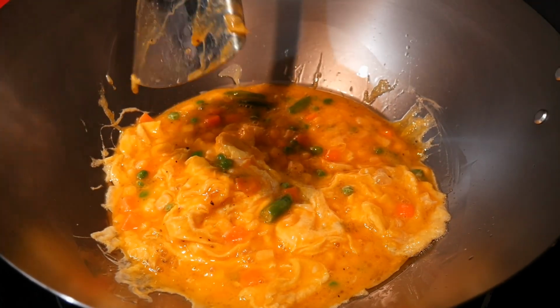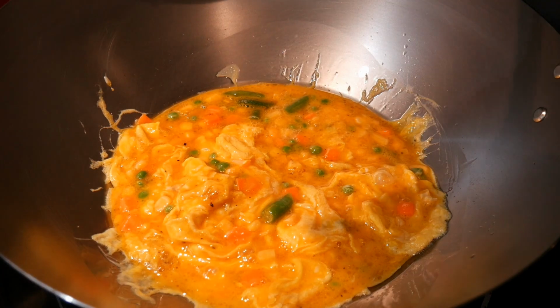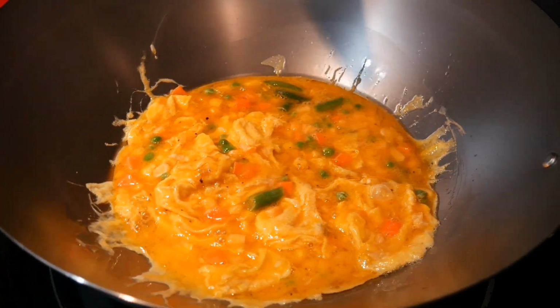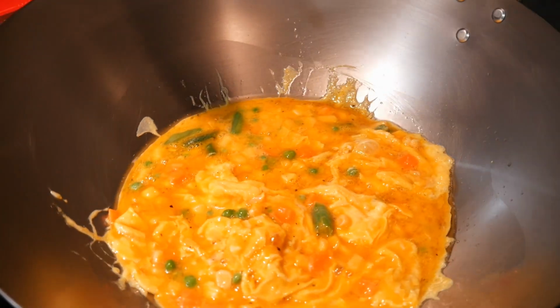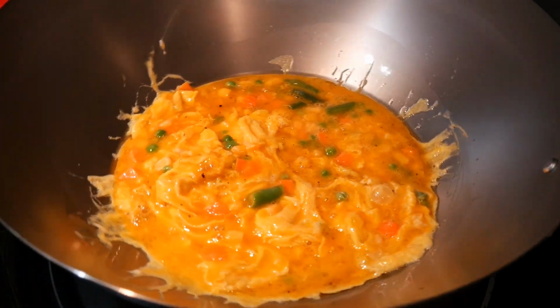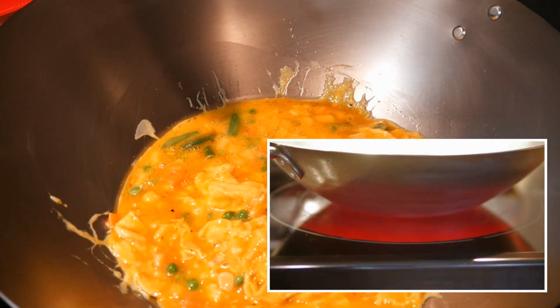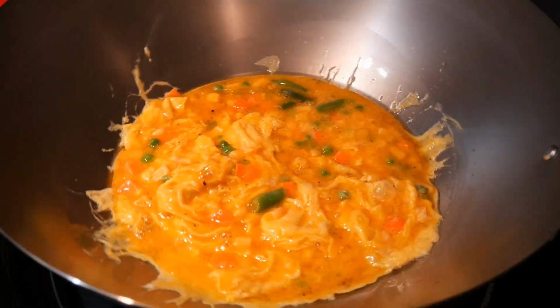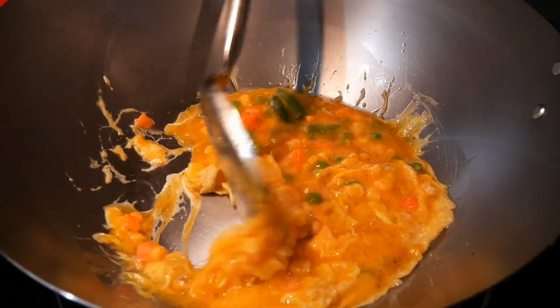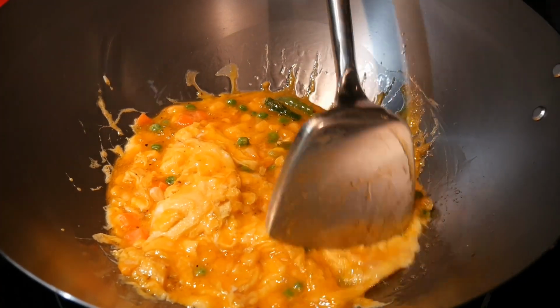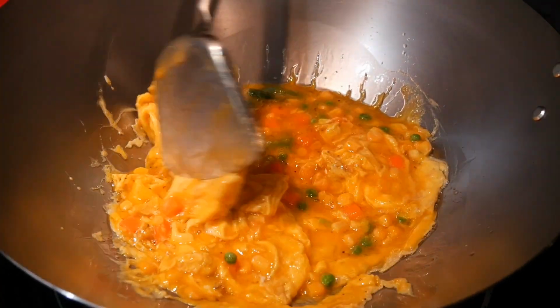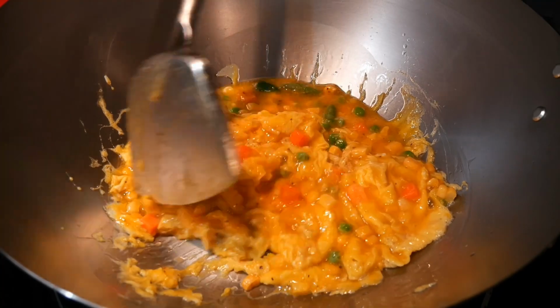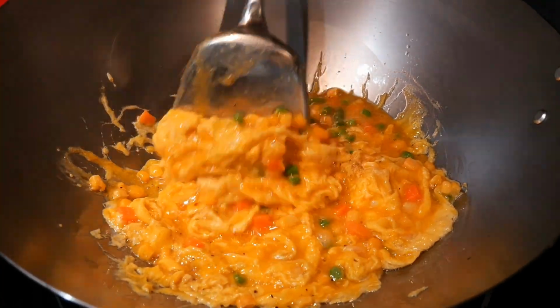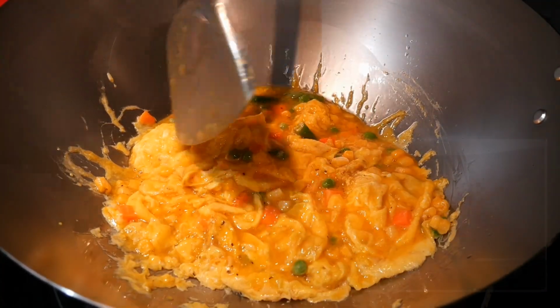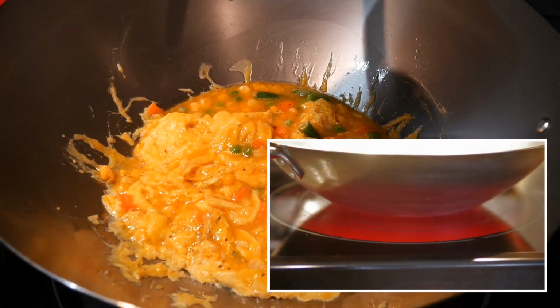While I cook, I notice one thing: the wok is not very steady. In fact, the wok starts to rotate. I'm cooking on a flat glass top electric range. The reason the wok rotates is that a carbon steel wok changes shape when it heats up. The bottom surface of the wok, which has the closest contact with the glass top electric range, will expand more than the periphery of the wok and will form a convex surface.